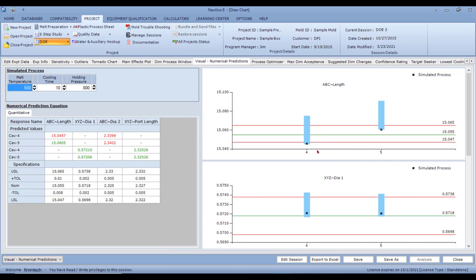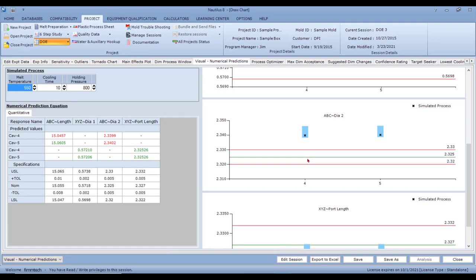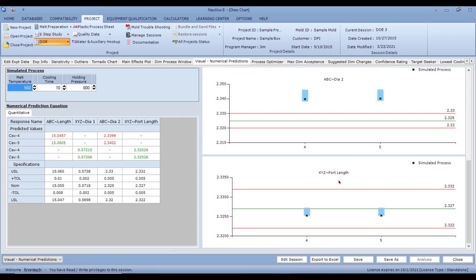A change must be made in the steel dimensions and/or in the product specifications. Changing specifications is almost impossible most of the time, so the steel has to be adjusted. Looking at the port length, however, the blue column is completely between the lower and upper spec limits — meaning if the part is cosmetically acceptable, it will also be dimensionally acceptable and will never go out of spec. In such cases you can eliminate or reduce inspection — perhaps measure only once per shift or once per day.